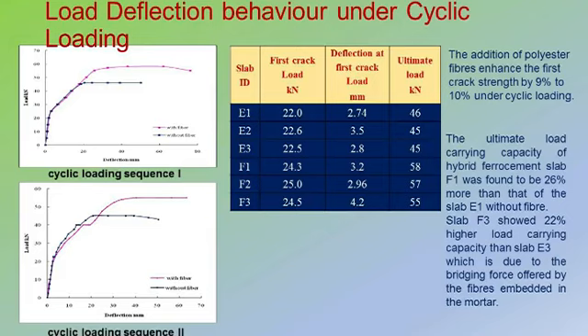So these are the first crack loads observed and the deflections observed. These are the ultimate loads. From this, it was concluded that the addition of polyester fibers enhances the first crack strength by 9% to 10% under cyclic loading. And the ultimate load carrying capacity of the hybrid ferrocement slab was found to be 26% more than that of the slab without fiber. And slab F3 with fiber showed 22% higher load carrying capacity than slab E3, which is due to the bridging force offered by the fibers embedded in the mortar.